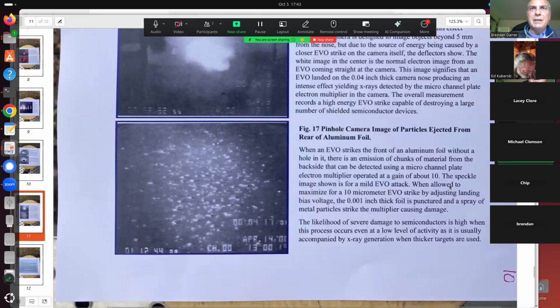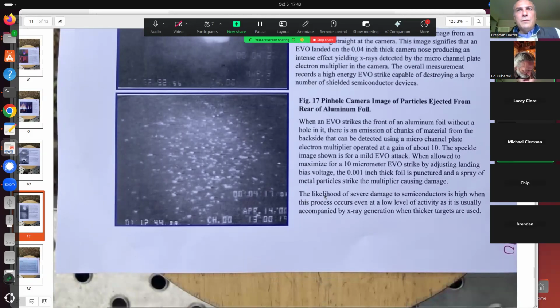When allowed to maximize for a 10 micrometer EVO strike by adjusting landing bias voltage, the 0.001 inch thick foil is punctured and a spray of metal particles strike the multiplier, causing damage. The likelihood of severe damage to semiconductors is high when this process occurs even at low level of activity, as it is usually accompanied by X-ray generation when thicker targets are used.